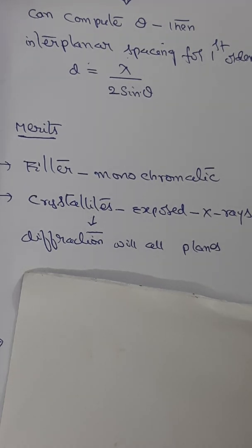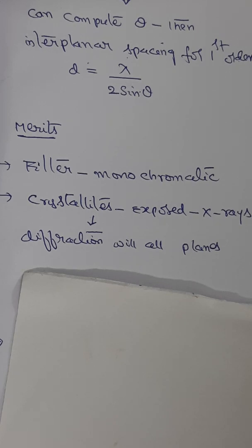The diffracted X-ray cones naturally make impressions on the film in the form of arcs on either side of the exit and entry holes, also with their centers coinciding with the hole. So the diffraction pattern helps us to calculate the angle corresponding to a particular pair of arcs, and it is related to the distance s between the arcs as 4 theta equal to s by R in terms of radians, because angle equal to arc by radius, where R is the radius of the camera, and the same thing when expressed in degrees, 4 theta will become s by R into 180 by pi.